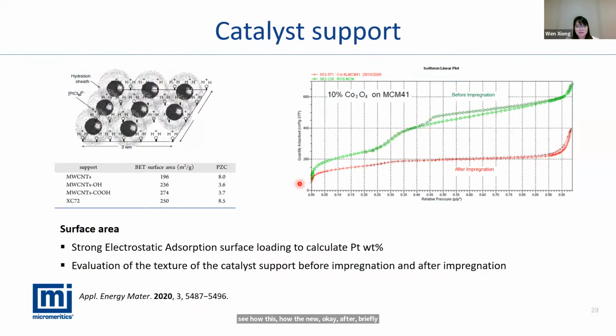After briefly introducing our 2930, now let's go to see some real application cases. First, let's start with our catalyst support. As I mentioned earlier, we use the chemisorption analyzer to check the catalyst support. We normally look at the support surface area. The left figure shows one example of measuring the BET surface area before synthesis of the support. The reason is that the authors were using a strong electrostatic adsorption synthesis method, so they have to know the surface area of the support to calculate the surface loading and the final platinum loading on the support.